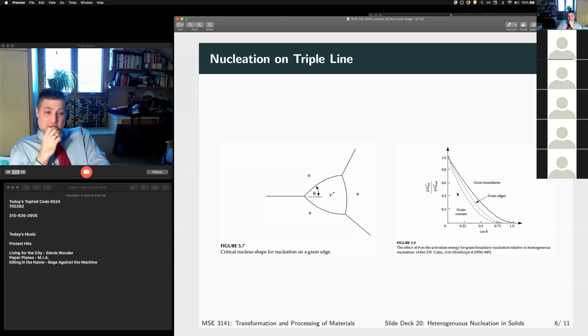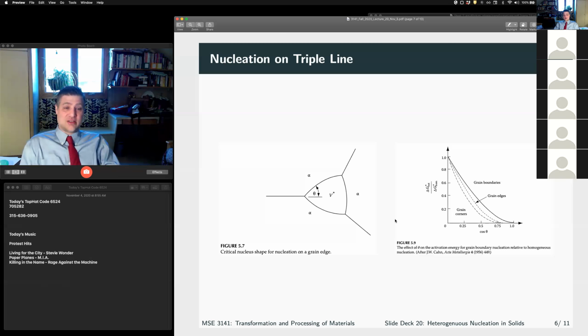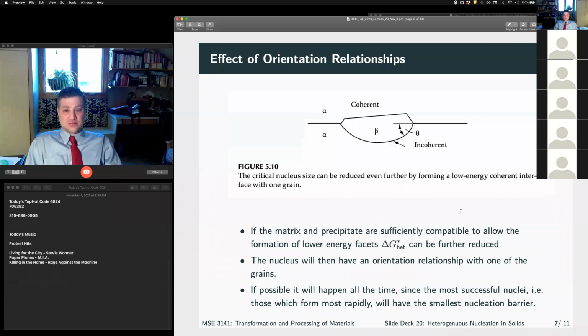Which brings up an important point: whatever is easiest to nucleate will. Anything that gives you a small advantage in nucleation, in delta G star, is going to completely dominate what you see when you look in the microstructure. So that's important. Most of the time we don't see multiple types of nucleation happening. It's winner take all. Whatever one gives you a slight advantage in terms of energy is going to completely take off.